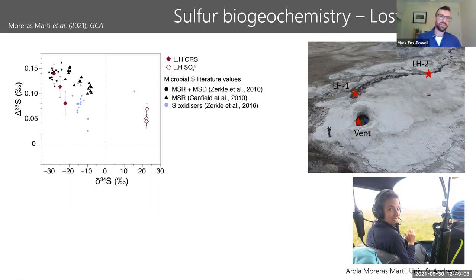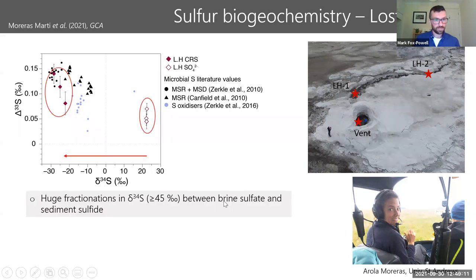She's produced these beautiful records of quadruple sulfur isotopes, looking at samples from the salt deposit here and showing that these really enormous fractionations between the sulfate in the brine and the sediment and sulfides that have accumulated in the sediment are really indicative of biological activity. So these deposits are recording biological sulfate reduction that is going on in the subsurface and is now being recorded in this surface deposit.